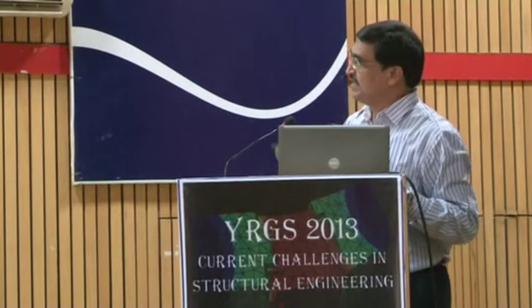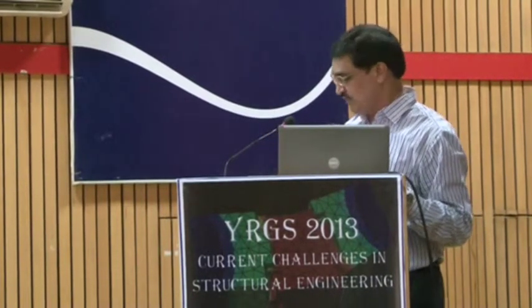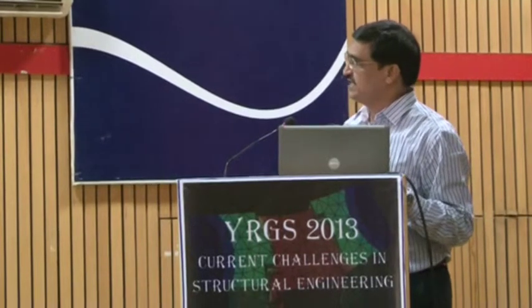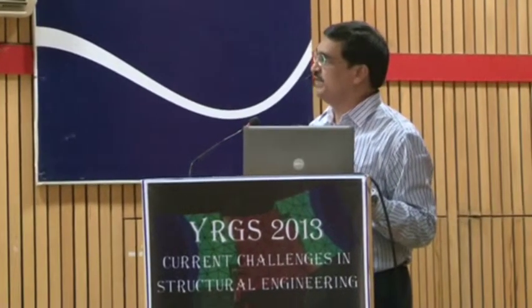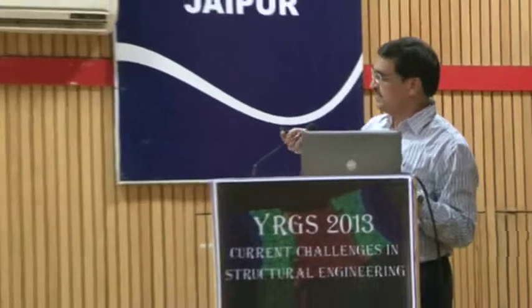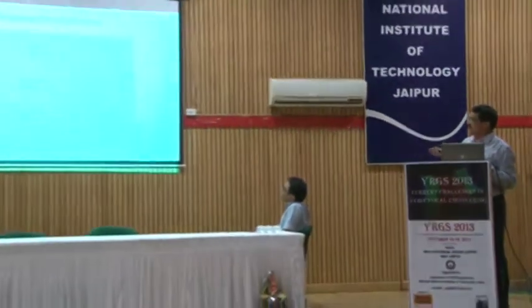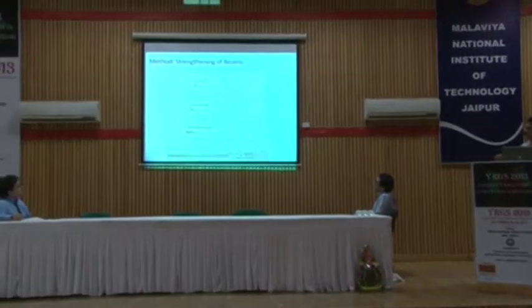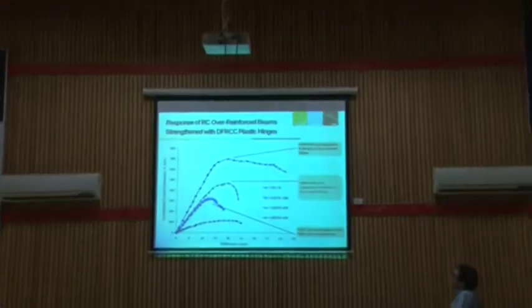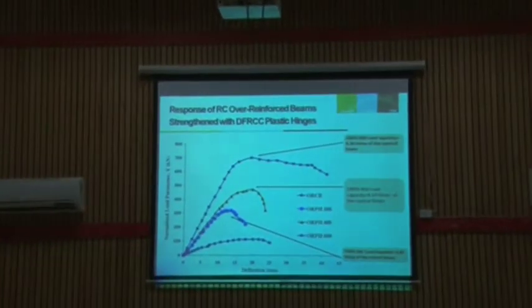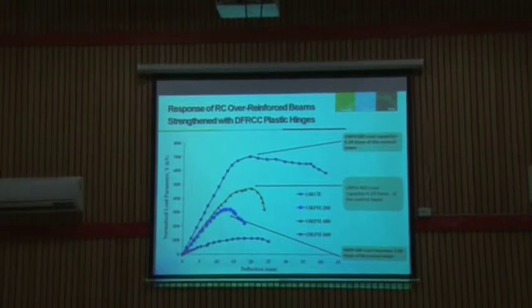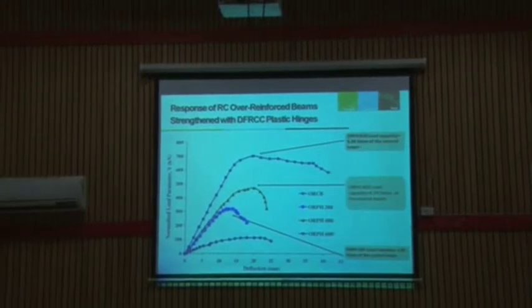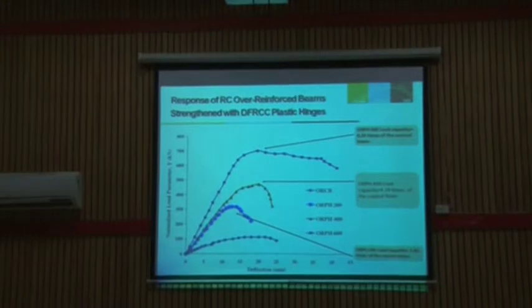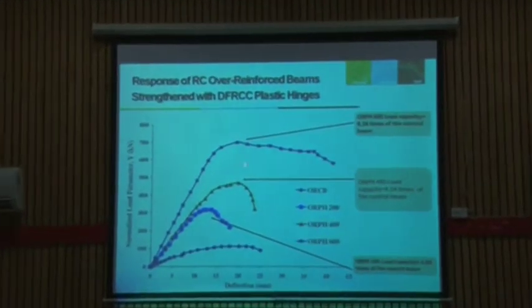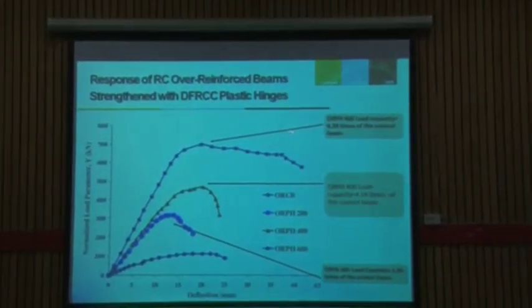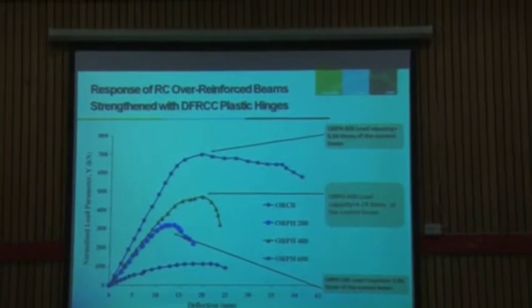So the typical FRP material plus ductile ECC can also show a very good improvement in strength and stiffness. Typical beams have been taken, under-reinforced and over-reinforced, with different loading combinations. Here we have taken ECC at a particular plastic hinge location. Then here we have taken ECC as layers, and we see that the response is found to be very good. Then we are plotting normalized strength parameters and deflections. For over-reinforced beams with a plastic hinge length of 600 mm, we find a very significant strength improvement, and we also saw that there is a significant amount of ductility available in the system.